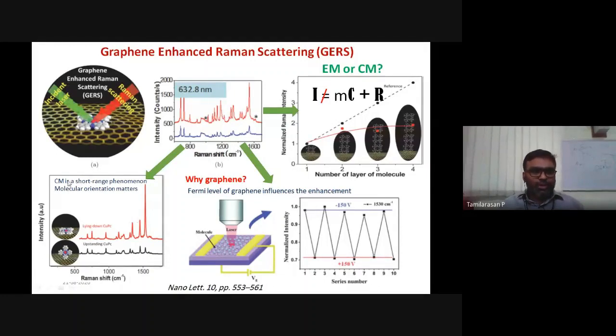And to prove this, there were a lot of questions about why graphene has to enhance the Raman signal. Of course, the enhancement is very small, like 10 power 2 times only, but still they have tried in several ways to prove that it is a chemical enhancement. In the first way, if you see the Raman intensity as a function of concentration, it has to have a linear regression, right? But when you put several layers of molecules, it didn't follow the linear regression.